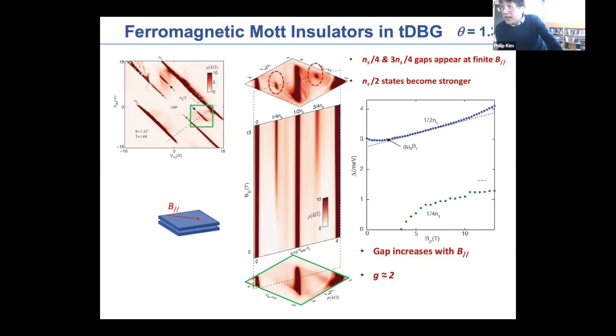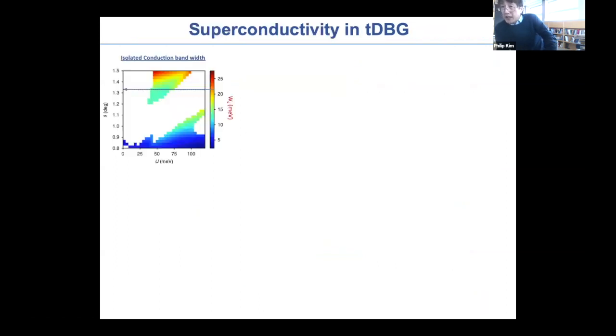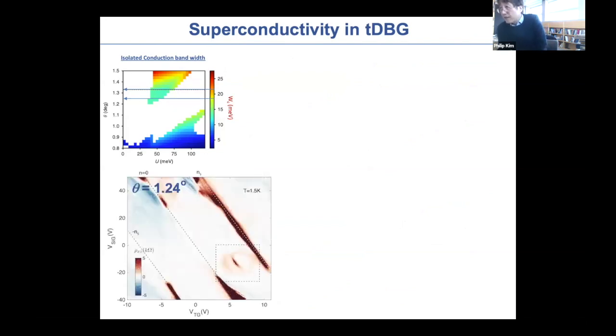Now, the natural thing we can ask is, okay, so we start to see that these gaps are potentially correlated effects. Then what if we go slightly away from this gap and dope these samples like the twisted bilayer graphene? Do we see something unusual? Indeed, when we tune our angle even smaller, such that the bandwidth becomes even smaller, we start to see very similar things. Again, there's a region that appears where this half-field correlated insulator appears. And it turns out this half-field correlated insulator is also spin polarized.